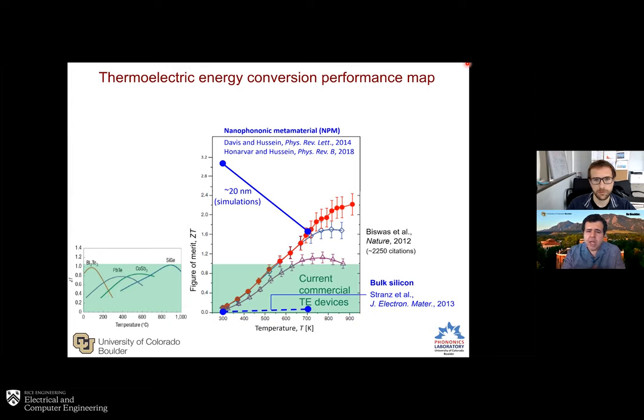in performance. It's also interesting, I should say, that not only can the performance be quite high with this path, but qualitatively the trend is very different. Typically the ZT value increases with temperature, because the T in ZT is temperature, whereas here we're looking at something that goes down. That's because, as I said earlier, we are utilizing wave phenomena, and when you increase the temperature, the scattering increases, so you get less of that wave phenomena. So it's interesting from several perspectives.